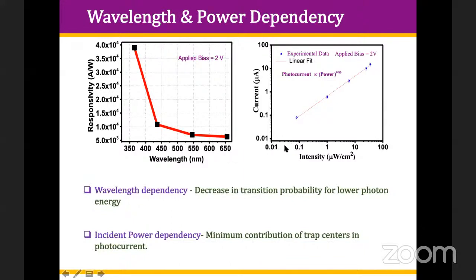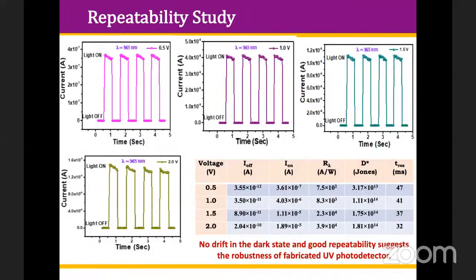Also, for the incident power dependency, you can say an almost linear response is obtained in the current with increase in the intensity of the UV light, which clearly shows that the contribution from the trap, because this is a more physics-based concept, the trap always participates in the photocurrent, but if the response is linear, that means the contribution from the trap centers where charges are trapped is going to be minimal, and the major contribution is from the band conduction in this case.